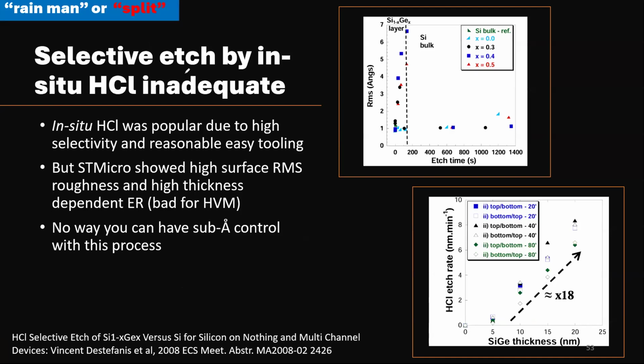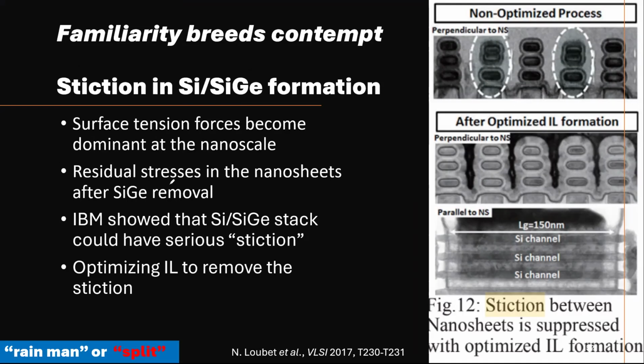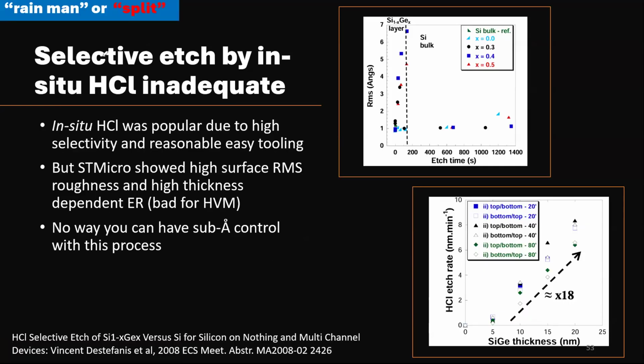And the issue developed later on is selective etch by in situ HCl. So you want to do sacrificial etch. You want to etch this one off, right? This had to be removed. This is what I call the selective etch, and classically use in situ HCl. In the early study it's fine, it's pretty high selectivity. You just need to add a small chamber or in situ process HCl vapor inside your SiGe chamber, that's fine, etch chamber. It's okay. But it turns out, no, it's not.